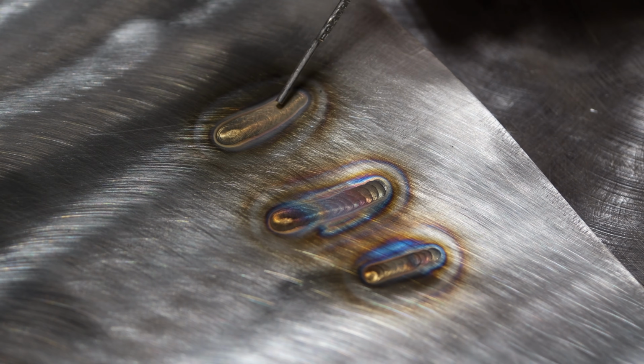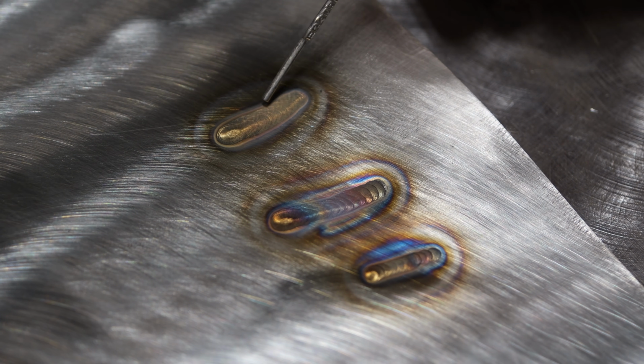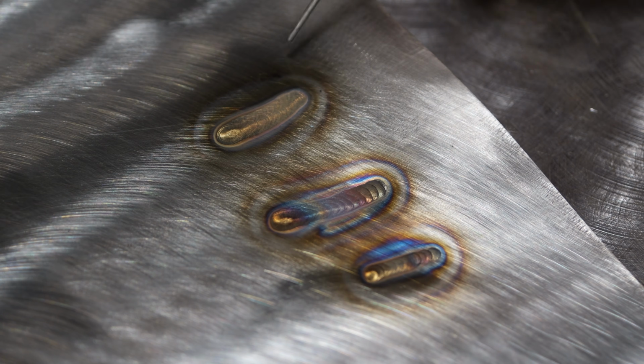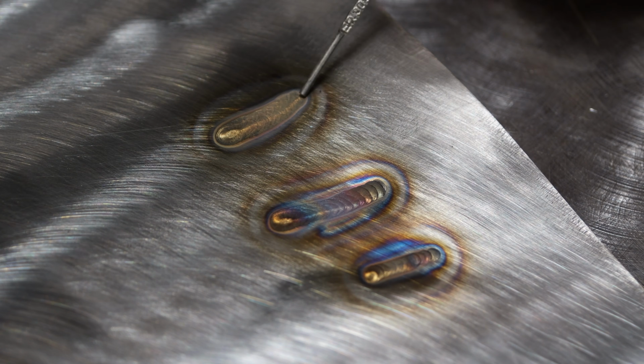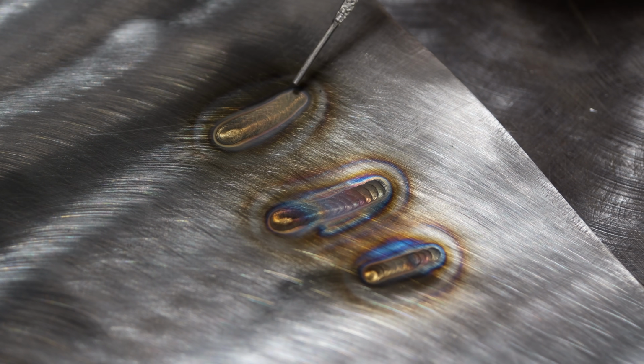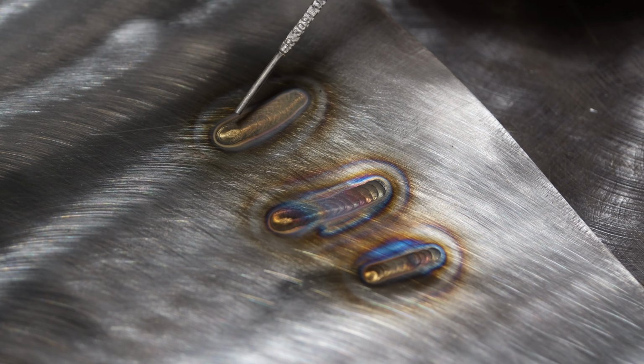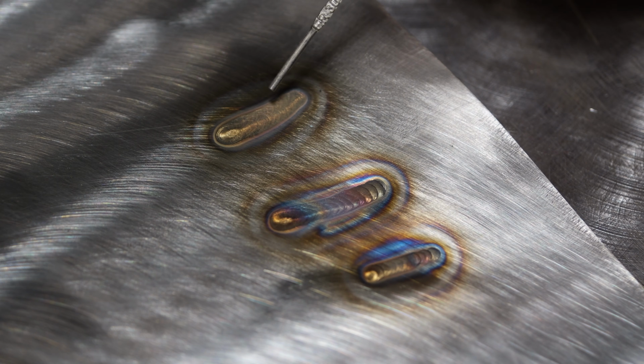So 60 amps was actually a little bit hot, so I was somewhere probably around 50 on it. This material is a little thinner than I expected. Anyways, this weld right here was done with the larger gas cup, and you can see a very consistent color. These are short welds, and I did that kind of on purpose to show how much better the shielding gas is with a larger cup.